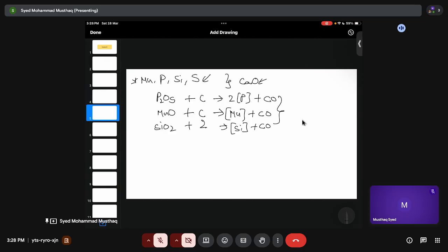And with increasing temperature, these things will get more probable. You are making sure the reaction moves forward. Because when you see the delta G naught values, it's mostly in the form of A minus BT. So the higher the temperature, the more this product will dominate, and the higher the product domination, the more negative will be the delta G naught value. Okay, so that is one point.